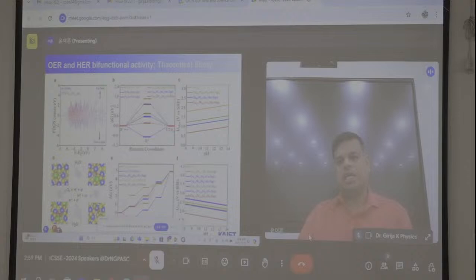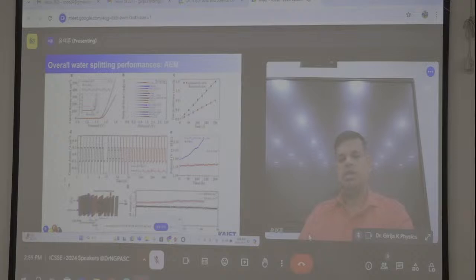But in other cases, we also do different pH. I told you different pH also, a universal pH. I also do the different pH with the HER and OER, and this is the mechanism of how oxygen adsorption and desorption happens. And we also do the full cell devices and reversibility test. When comparing to the commercial one, the reversibility is highly maintained for the overall water splitting, and the durability for more than 200 hours is stable.